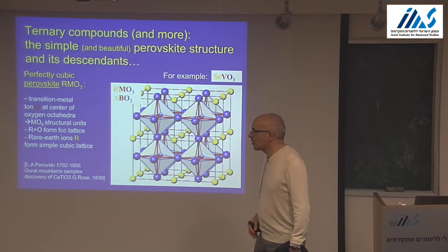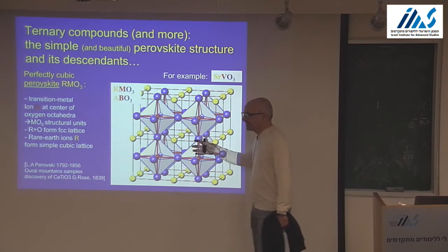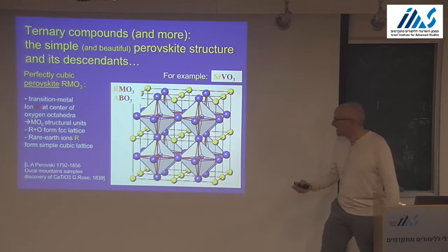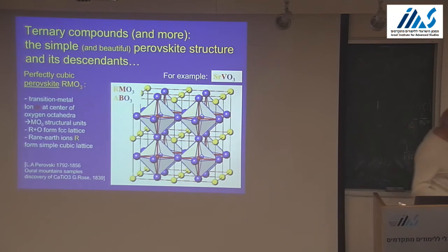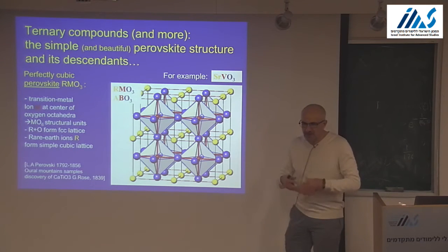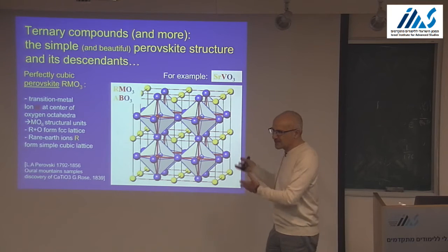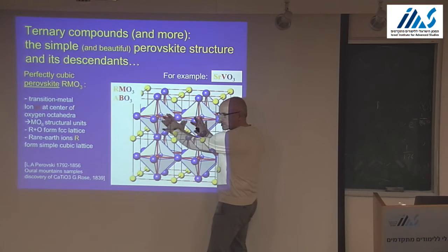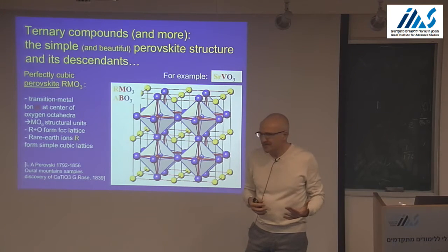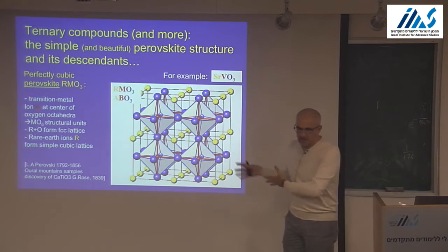No, it's not a model. It's a reality, you know. For example, if we take strontium VO3, in contrast to the Hubbard model, this is not a model. Strontium VO3 is exactly in this crystal structure with exact cubic symmetry. Many, many of the ABO3 oxides actually do take this crystal structure with a little twist, which is that these guys would rotate a little bit and tilt a little bit, hence lifting weakly or more strongly the cubic crystal symmetry. Okay? So that's really what many oxides do.